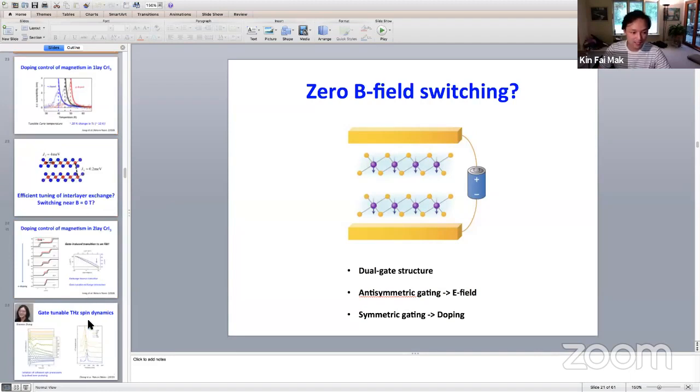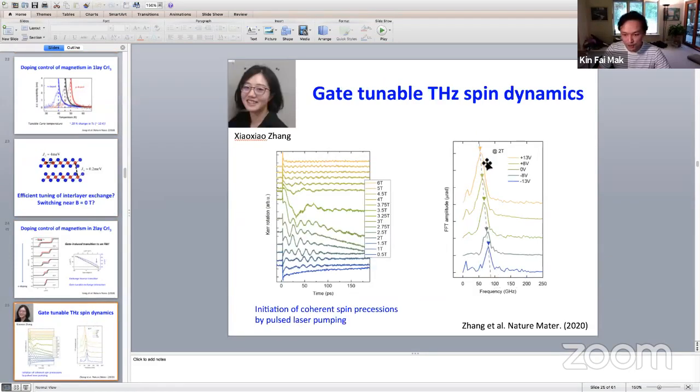But you can see in this result here, we have measured the spin wave frequency in this system. Because of the antiferromagnetic exchange and the large anisotropy in the system, it is rather high. The frequency is close to 100 gigahertz. So it's very difficult to access this frequency range with a conventional RF technique. So I doubt that one can easily use RF voltages to create spin wave excitation in this system. It's not impossible, but it's difficult.